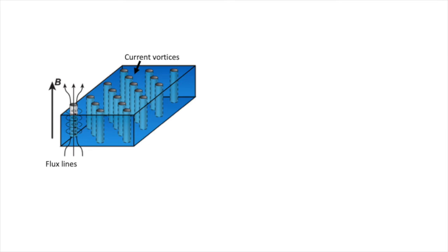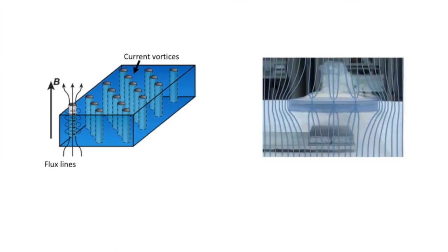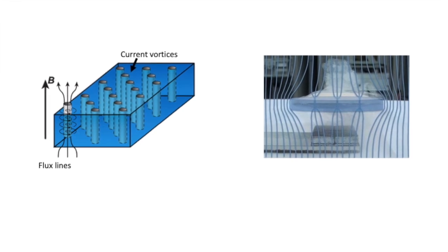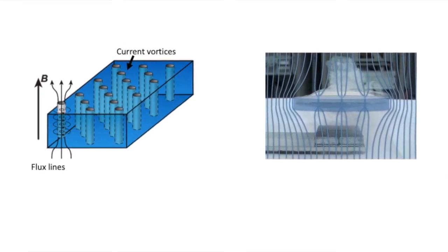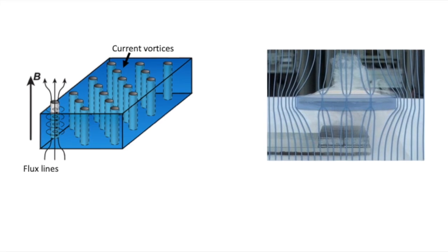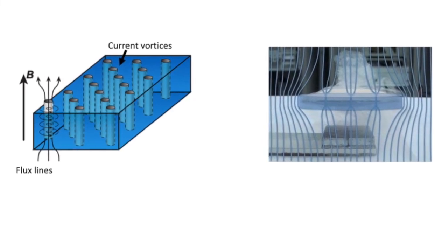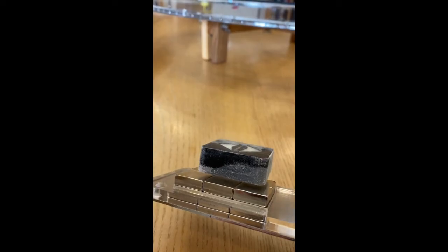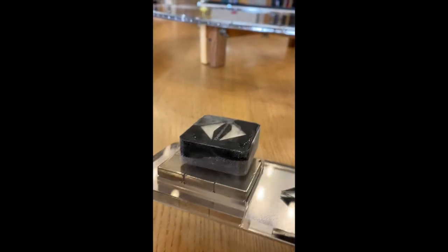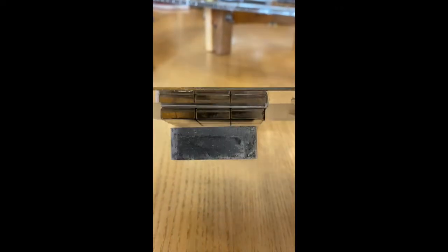However, this magnetic field penetration can only come in discrete bits of field leakage, whose little vortices of current surround so-called flux lines that go through the superconductor. These flux lines can actually repel each other and form pretty ordered arrangements. Even more, these flux lines can get pinned in place due to imperfections in the superconductor material. When the flux lines get pinned, the magnetic fields don't like to move around, and this causes the superconductor to get locked in place above the magnet. Locked relative to the magnetic field, even when it gets turned upside down.